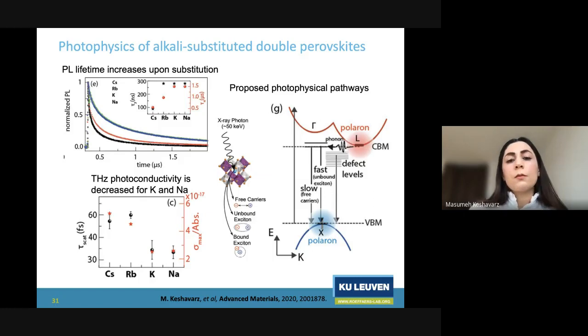To conclude, we put together the results of all these measurements in different wavelength detection windows and time domain terahertz measurements. We could actually propose this model for the system. We could prove that there are large polarons forming in these systems, which is not strange looking at their giant electron-phonon coupling constants. Then there are defects in this system causing the very fast decay lifetimes. Then there are some fast and slow decay lifetimes, where one originates from the bound and unbound excitons, and the slow one, which is within the microsecond range, originates from the free carriers.